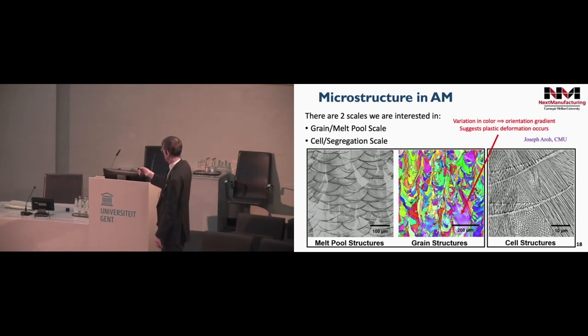But if you look at certainly some of the larger grains, and this is of what we call inverse pole figure color, which tells you something about the crystal surface that's exposed, you realize that the color is not uniform. It's shaded. There are variations in that color, which tells you that there are orientation gradients, and the only reasonable way to understand those is as those grains containing dislocation structures, which rather strongly implies that plastic deformation has occurred. Well, that's yet another topic I can't explain directly today. There isn't time, but we can come back to it in a later lecture. And then if you magnify further, then particularly the FCC metals, you essentially always see a cell structure because of the microsegregation that almost always happens. So that's a very quick introduction to the microstructures.